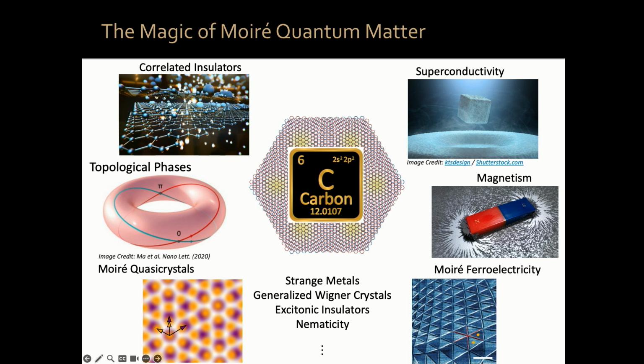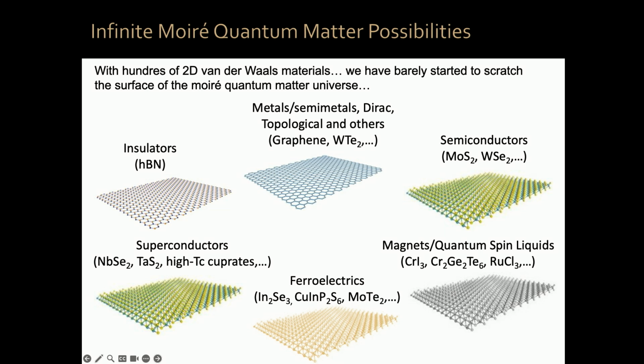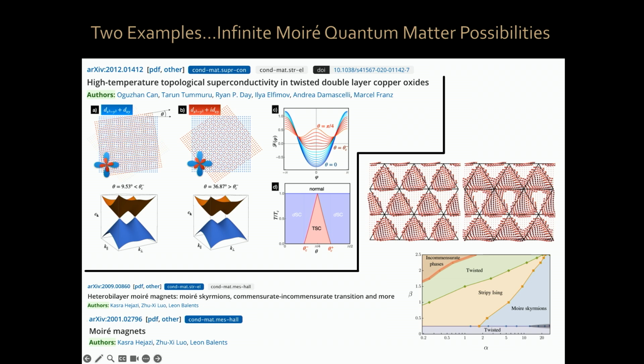But we have hundreds of 2-dimensional materials, many of which, in their elemental, single layer form, can be quite exotic. So as you can imagine, now people are slapping on top of each other and twisting every possible combination of 2D materials. You have hundreds of people trying different angles and combinations, to see what we can discover. Some of the things that have been theoretically predicted are high temperature topological superconductivity when you twist double layer copper oxides. High temperature superconductors are layered materials; you can twist them and change the type of superconductivity you get. If you have 2-dimensional magnets, you can also twist them on top of each other and create something known as Moiré magnets, with Moiré skyrmions and Moiré physics in their magnetic properties.